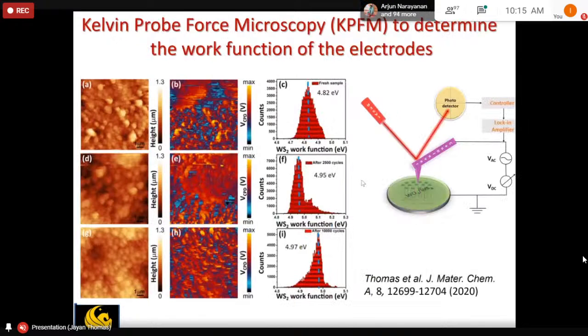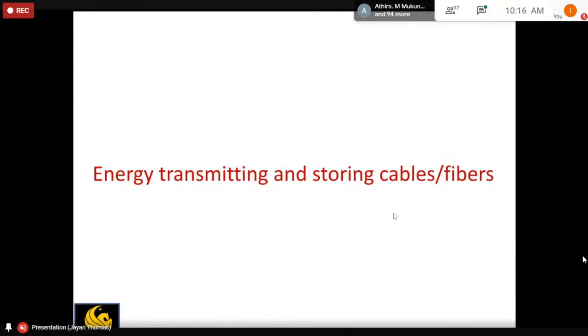And how can you measure this work function? This work function can be measured by a technique called Kelvin probe force microscopy. It is a type of atomic force microscopy, and you can measure the work function of this material. And very recently, we published a paper on how we can do this work function calculation, and that can be used to tweak the properties of supercapacitors.